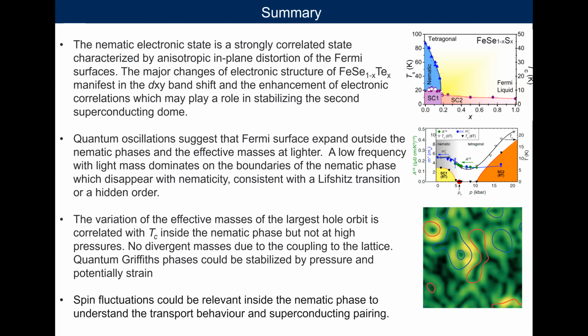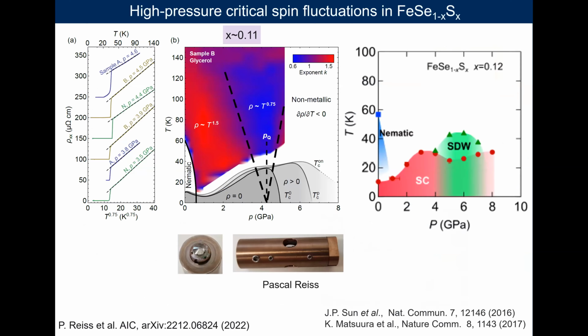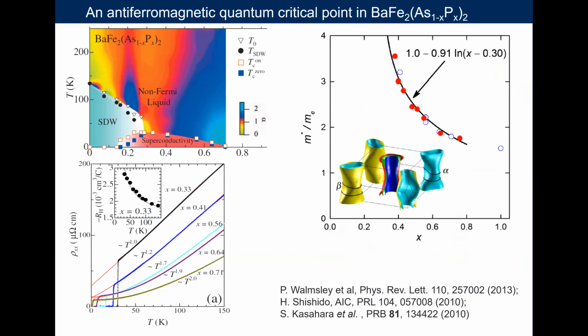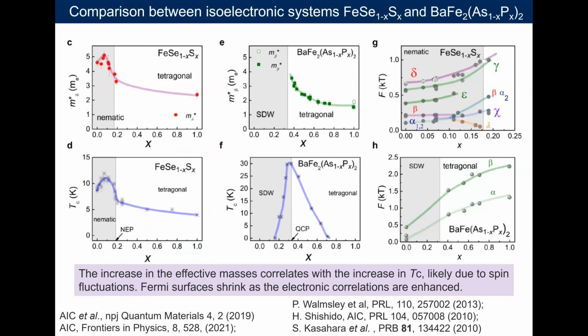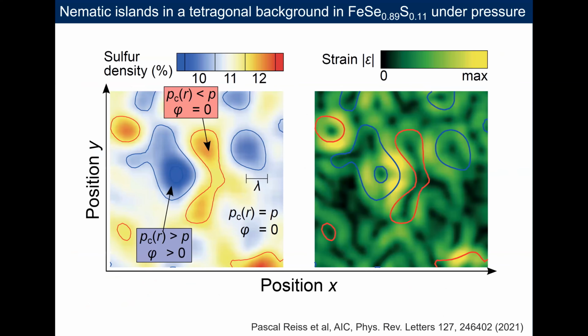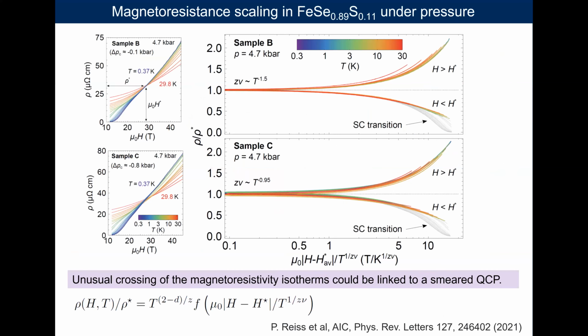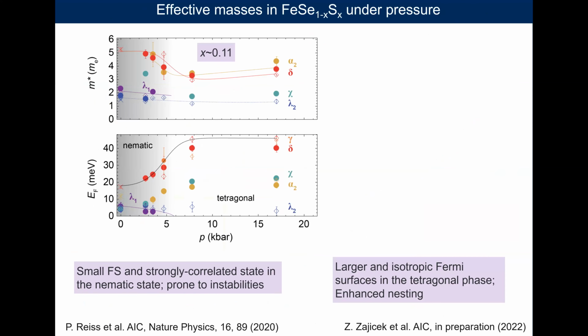What's happening to the Fermi surface in the high pressure region where Tc goes up a lot? Is it staying the same or is it evolving? So at high pressure, up to the pressure we managed to measure, which is only about 20 kilobar, we see that the Fermi surfaces usually increase in size. So they keep expanding. Is that both electron and hole pockets? Yes, they just expand more and more. Okay, very good.